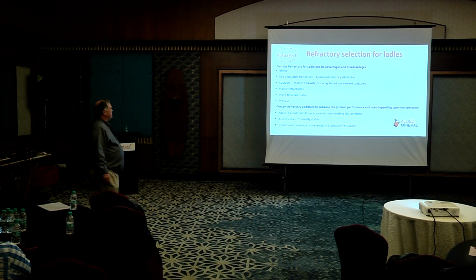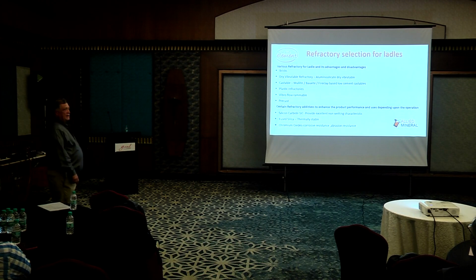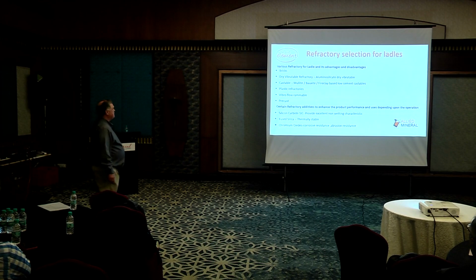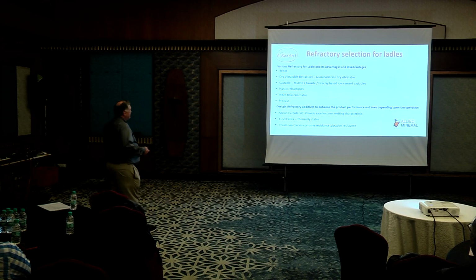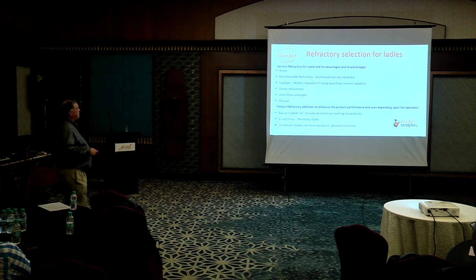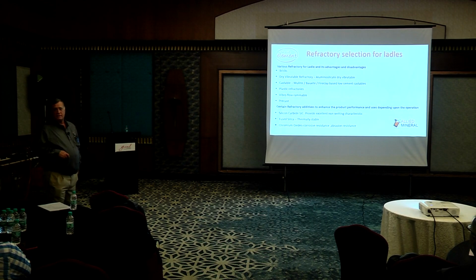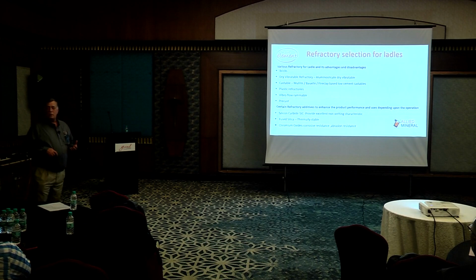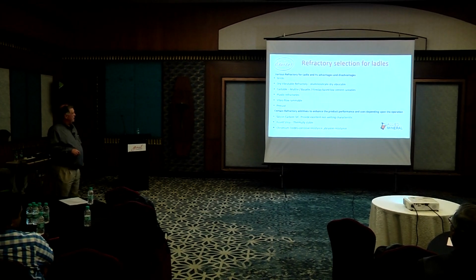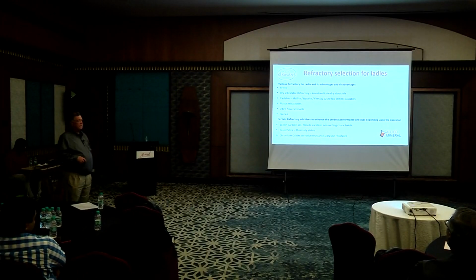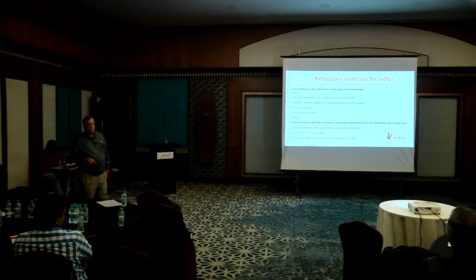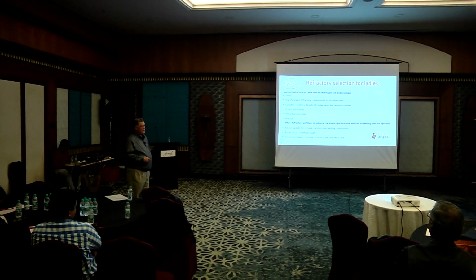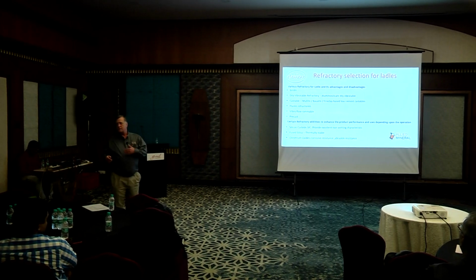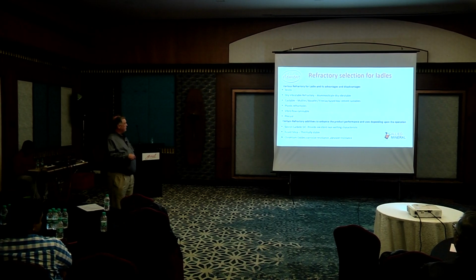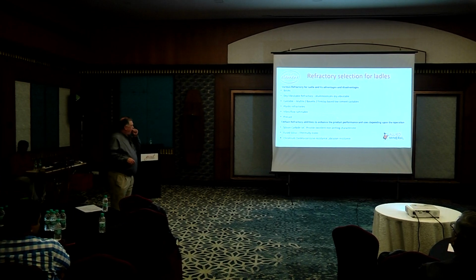So, refractory selection: various refractories for ladles and their advantages and disadvantages. You have bricks, dry-vibe, castable, plastic. This is called Vibraflow, which is a product that we have, a kind of vibration plastic, basically. Precast. Then there are certain additives that you can put into the refractory to enhance the performance depending on your operation. For ductile iron, you use silicon carbide to stop the buildup.